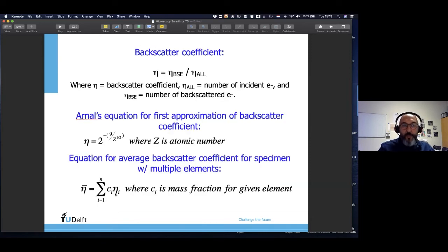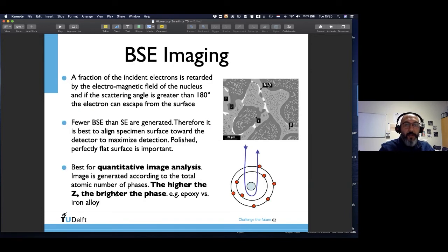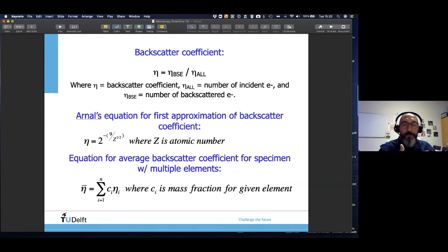Speaking of backscatter coefficient, again, as I told you before, it is all about the mean atomic number. So the higher the mean atomic number, the brighter the phase; the lower the mean atomic number, the darker the phase. And this is quite advantageous for concrete people or people who are dealing with porous materials. Why? Because those pores we are impregnating with epoxy, right? And that epoxy has a super low mean atomic number. So what's the advantage then? Of course, then we will see all our pores very dark compared to the rest. And that helps us to isolate the porous part and calculate our porosity, for instance, when we do image analysis.